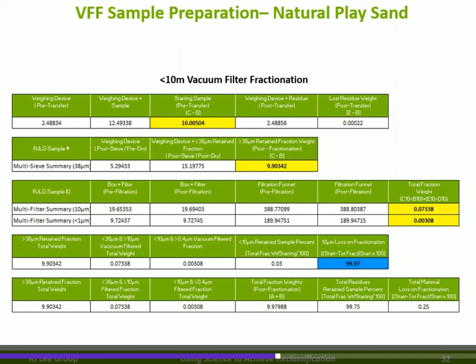So how does this lay out when we're done? For example, at the top, we start with 10 grams of natural play sand, and we fractionate it through the sieve. We end up with 9.9 grams of greater than 38 micron. On the right, we end up with 73 milligrams of 10 to 38, and 3 milligrams of 0.4 to 10. Our fractionation total is 99.97%. In other words, there's only 0.03% respirable particulate in this material. You've already cleared GHS. It cannot possibly be above 0.1% if you only have 0.03% in the respirable fraction.